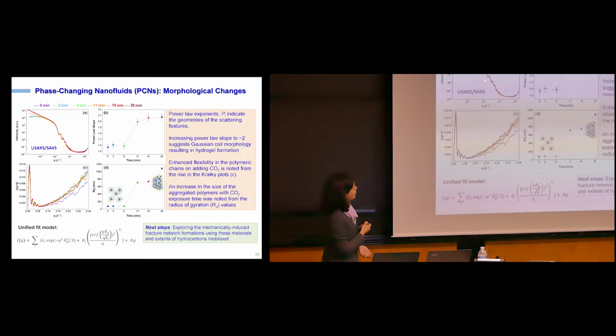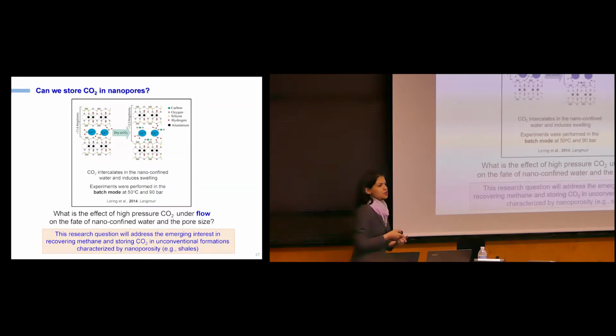And what we find is that these are the small angle and ultra small angle X-ray scattering curves. These undulations that you see here are a result of scattering from the silicon nanoparticles. And here are some of the features that we see. We attribute that to scattering as a result of the hydrogel formation. So we can extract things like power law slopes and effective dimensions of these materials, and we basically find some of these hydrogels forming. In the interest of time, I'm going to move forward and give you just a few more examples. That was just one example of some of the materials that we're probing to perturb the subsurface environment, if you like.